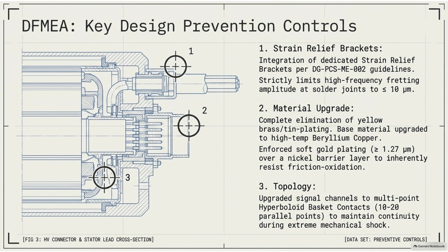What replaces it? They upgrade the base terminal material to a specialized alloy called beryllium copper, often referred to as BeCu. Beryllium copper. I know beryllium is heavily used in aerospace and satellites. It has to be significantly more expensive than standard brass. It is exponentially more expensive and far more difficult to machine. Yeah. But beryllium copper possesses a unique metallurgical superpower. Precipitation hardening. What does that mean for the connector? It boasts incredibly high tensile strength and elasticity, meaning it acts like an indestructible spring. Most importantly, it retains that massive spring force even when subjected to continuous 150 degrees Celsius temperatures. It never relaxes its grip on the connection.